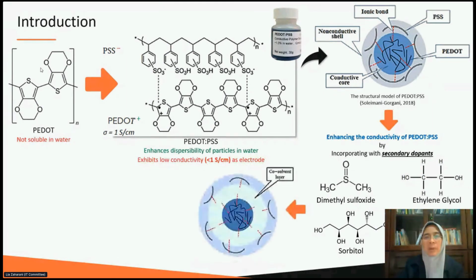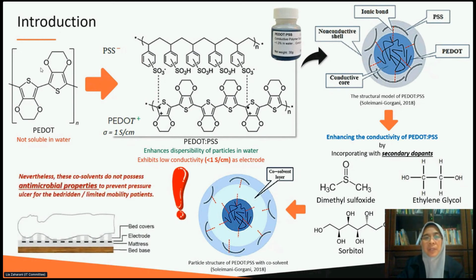So in this model, oligomer PEDOT segments are tightly bound by ionic interactions to PSS chains of much higher molecular weight, and that forms core-shell structures. So the high conductivity of the PEDOT:PSS dispersion can then be attributed to the arrangement of the PEDOT chains within large tangled structures of loosely cross-linked, highly water-soluble particles. So the PEDOT:PSS has a tertiary structure with a diameter of several tens of nanometers, where hydrophobic PEDOT molecules aggregate to form a physical cross-link between the PSS chains in water.